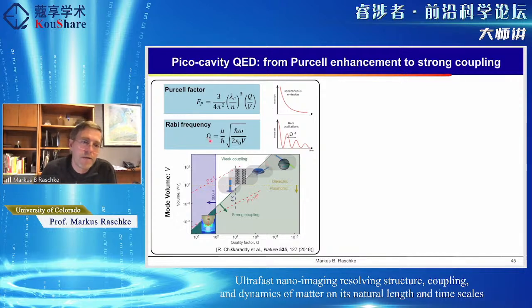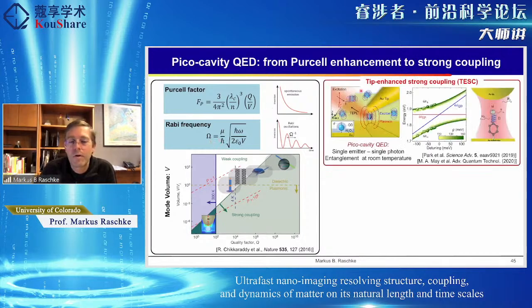And we could show that with these very small mode volumes, even at room temperature, we can actually achieve strong coupling. And we term this tip-enhanced strong coupling, where in this very small mode volume between the tip and the metallized substrate with quantum dots, we can achieve strong coupling of a single emitter. We showed this a couple of years ago, and now we are extending this in combination with molecular systems and looking at coupling between the vibrational and electronic degrees of freedom in strong coupling. And we can do this also just in the mid-infrared, probing vibrational excitations.